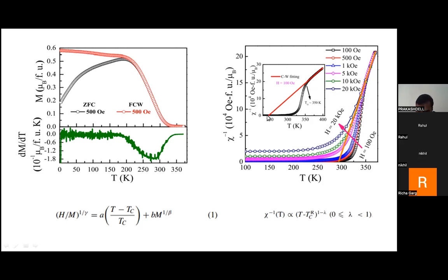What do I want to say? Here we have gone to the transition at 274. After that, we expect that the system should behave like a paramagnet, but it doesn't. It will start to behave like a paramagnet only after 350K. But if you analyze the material in a conventional way, you will interpret that the system has gone to the paramagnetic phase at 274K, which is wrong.